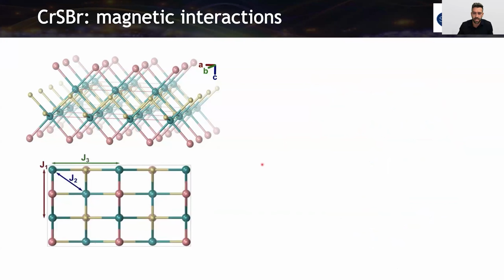Then regarding the magnetism, these are the first neighbor, second neighbor, and third neighbor interactions that are the most important in this material. We can observe that first neighbors are these two atoms that are contained in this line along the A-axis. So this is J1. J2 is between the chromiums that are from different planes, these two, and J3 is along the B direction.